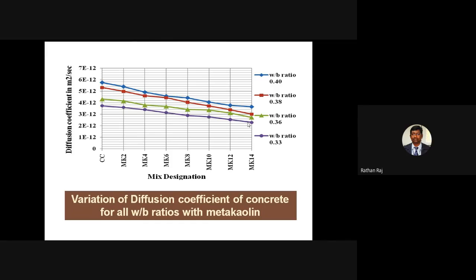As we already know, when we use some supplementary cementitious material in the concrete, automatically the diffusion coefficient value is decreasing. The reason is that the supplementary cementitious material has a large amount of silica content. So there is some free calcium hydroxide left behind. It is reactive, and there is reactive silica present. So when we create the reaction of the calcium hydroxide, it will react with the silica content and lead to denser concrete and increase the strength of the concrete.